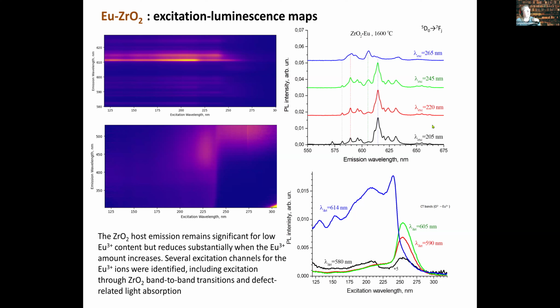But if we check all photoluminescence spectra taken under different excitation, these spectra were extracted also from this mapping, and measured additionally during the usual measurement as many people do. And you can see that we have some specific excitation between 200 nanometers and 250 nanometers. The spectra are quite similar, the black, red, and green ones. And when we switch to higher excitation wavelengths, we have differences in the luminescence spectra.